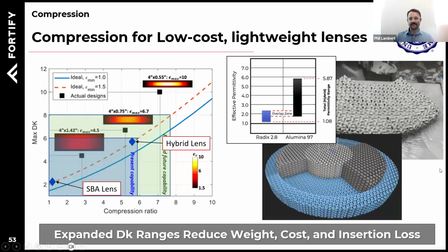And here's a great example of some work we did at the University of Notre Dame, where if we looked at that switched beam antenna lens, we had a compression ratio where the max dielectric constant and the compression ratio is about 1. But if we introduce a maximum dielectric constant of around 6, we can compress it by 5 to 6x in one axis. And so that means we can get to much lower form factors by leveraging all the phase change that happens in those higher dielectric constant materials. And what we had to do is make sure we had an overlap zone of dielectric constants, so we had a smooth gradient within that design.